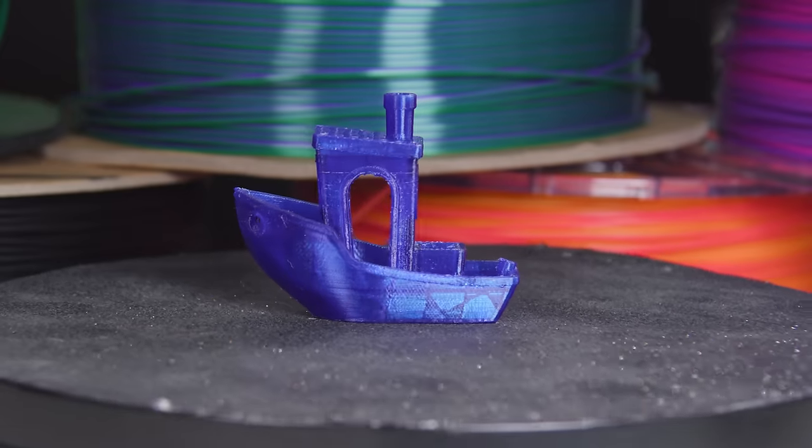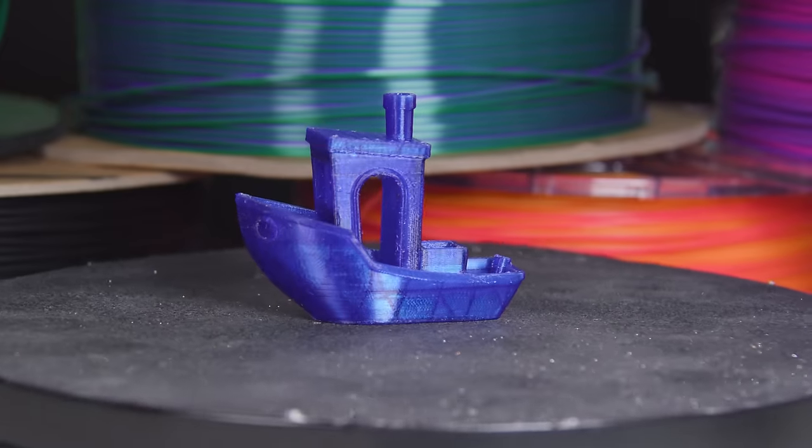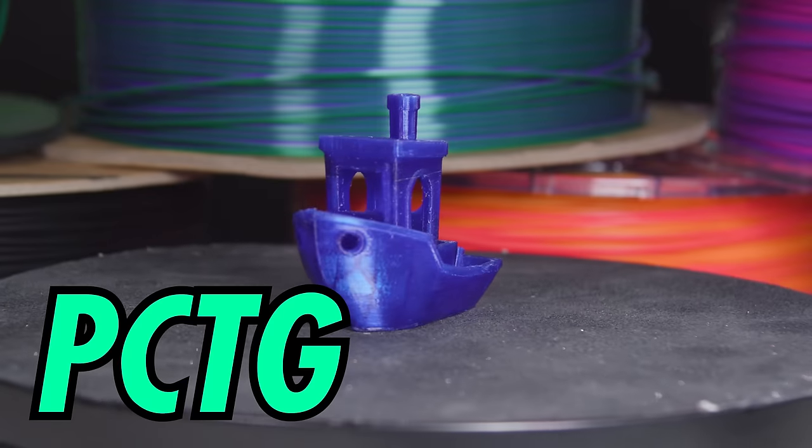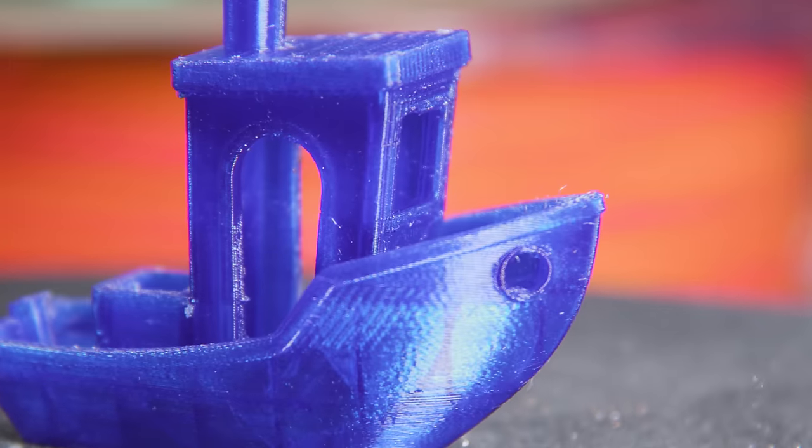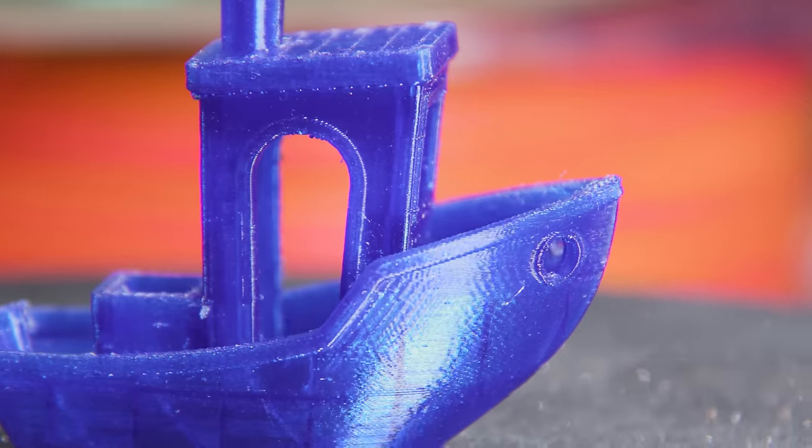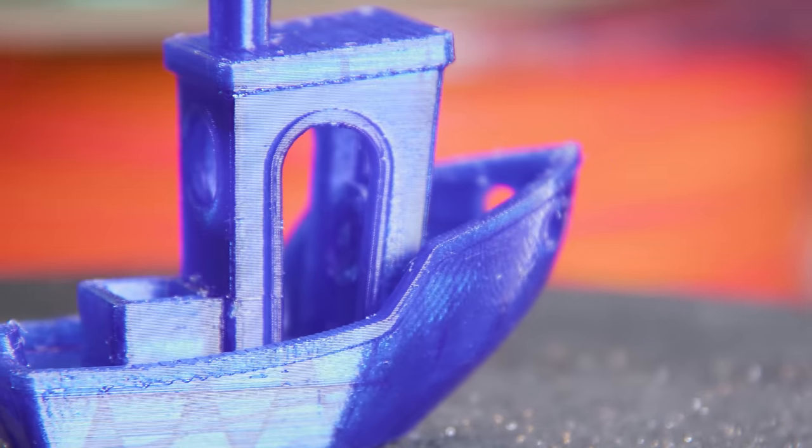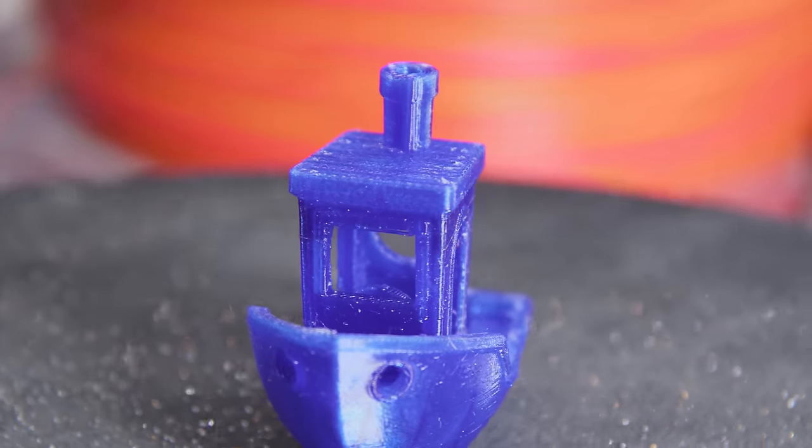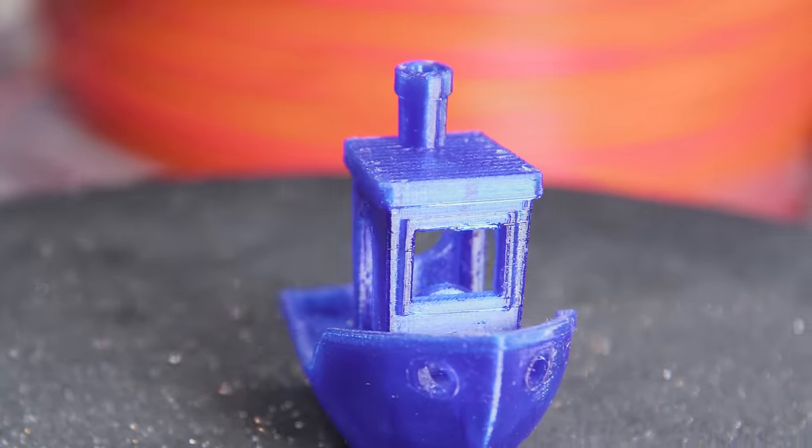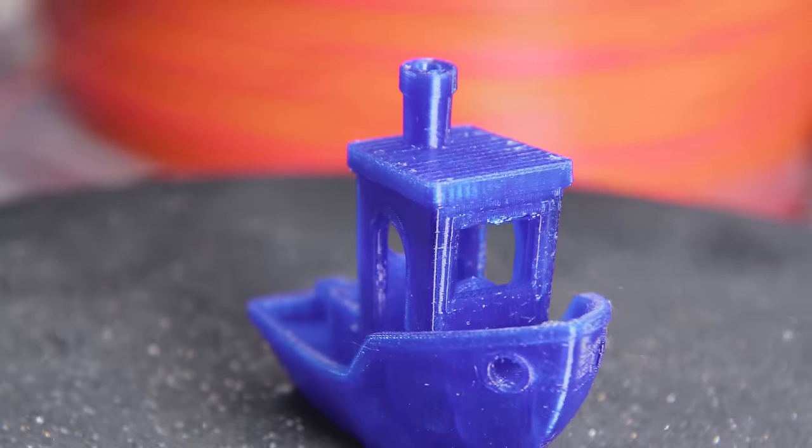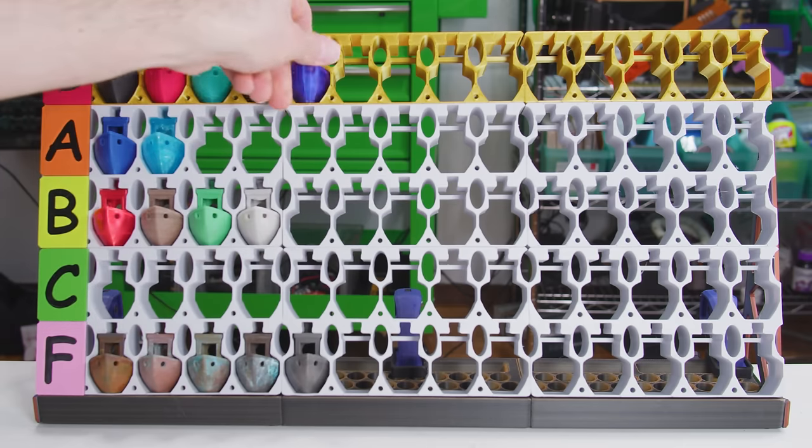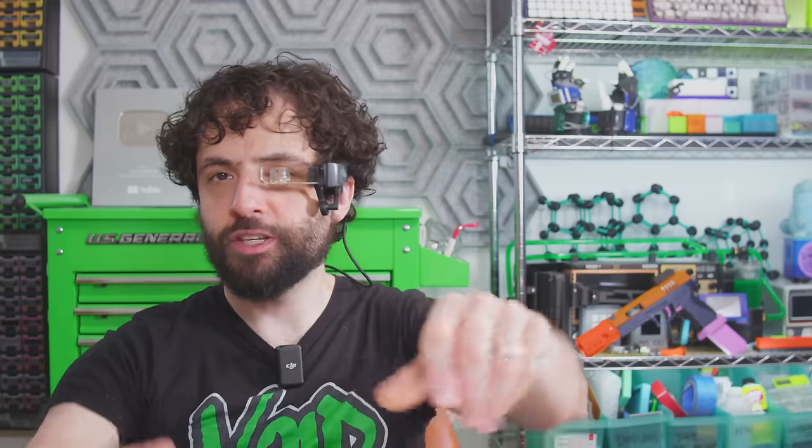But allow me to introduce PETG's younger, better brother, polycyclohexylene dimethylene terephthalate comma glycol modified. Everything PETG does well, PCTG does better. Everywhere PETG fails, PCTG is, like, mildly inconvenient. This stuff takes an insane beating, it gets waterlogged a third as quickly, and it is one of the easiest filaments to print. No warping, minimal sagging, and almost perfect layer adhesion for consistently strong prints in all directions. PCTG gets the top of S tier because it's as close as you can get to a perfect filament. Really, it's only downsides are supports are hard to remove, it's expensive, and it's really hard to find, which is probably what makes it expensive. I truly cannot comprehend why the market hasn't caught up yet. I suspect it's only a matter of time.